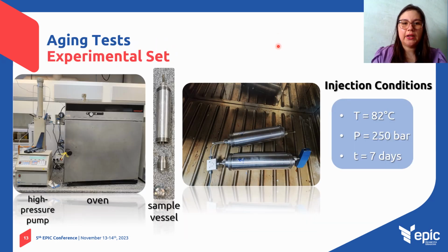To investigate the stability of the chemicals at the closest injection conditions, maximum temperature and pressure of injection, with information provided by Equinor, the aging tests of the chemical fluids were conducted at 82 degrees Celsius and a pressure of 250 bar for 7 days, using a system consisting of a high-pressure pump, an oven to maintain the temperature of the sample along the analysis, and a sample vessel to store the chemicals during the experiment.